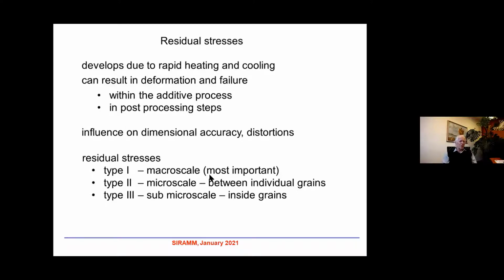We distinguish residual stresses according to three types, namely type 1, type 2, and type 3. Type 1 are macro-scale stresses. They are most important, and they can change dimensions or cause distortions of the component. Type 2 are microscale. They are stresses between individual grains. So they can influence, for example, fatigue initiation and mechanisms of damage.